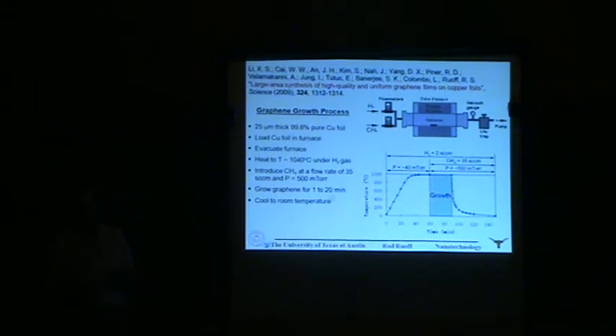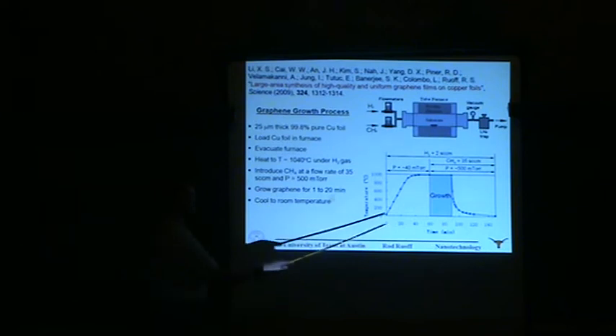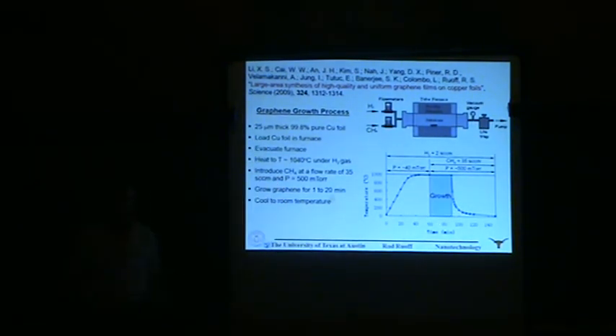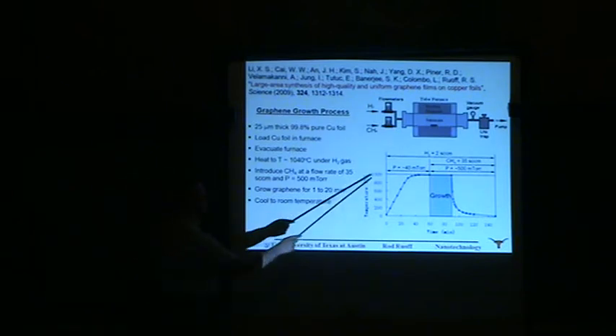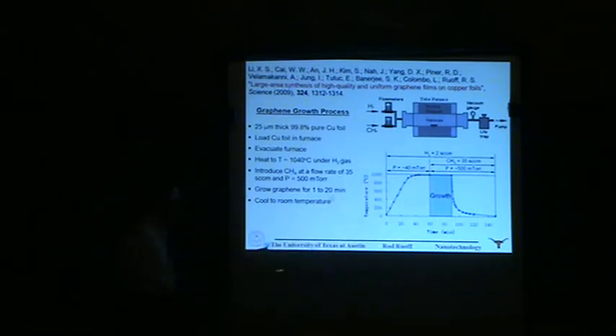Our original thinking was, per that binary phase diagram, that they would go down into the copper. And then when we cool down, growth would be occurring by precipitation from the bulk. But the picture is different because we learned that actually growth occurs at temperatures such as 1,000 degrees C, and the growth is entirely surface mediated. There's no dissolving of carbon atoms down into the bulk copper. And I'll prove that in a few slides by a new experimental method we developed.